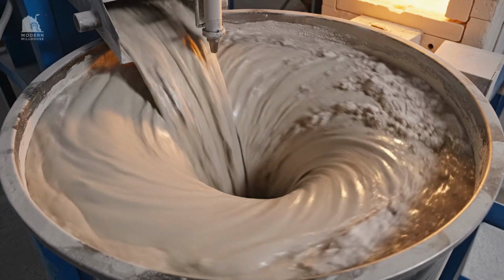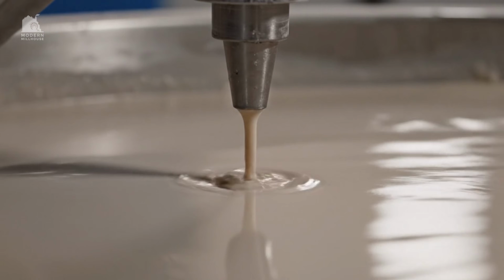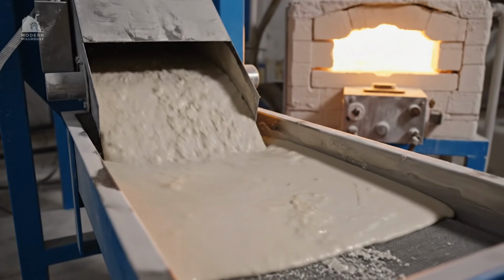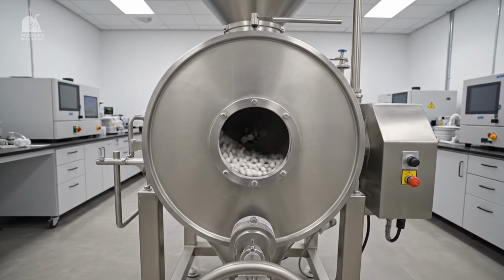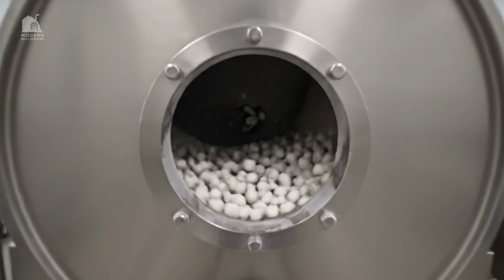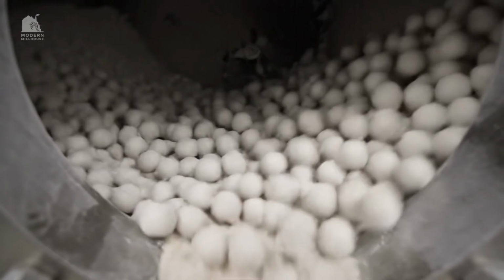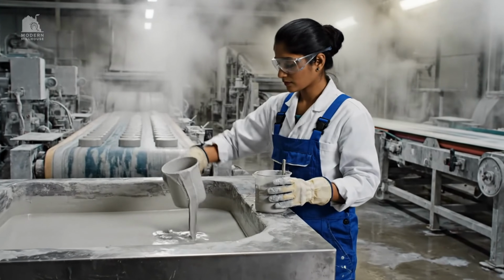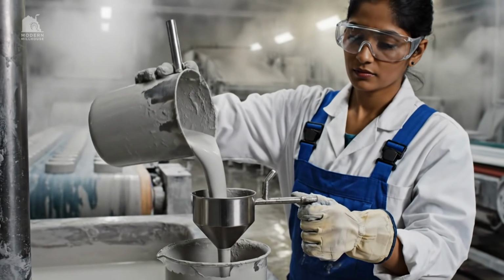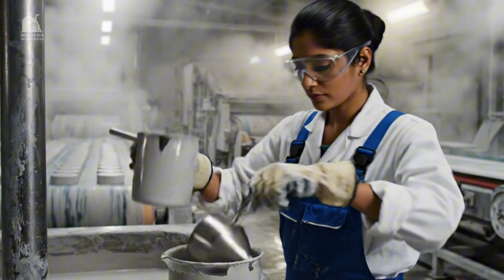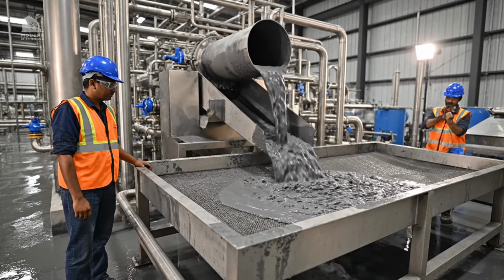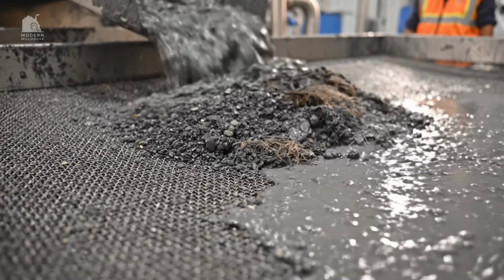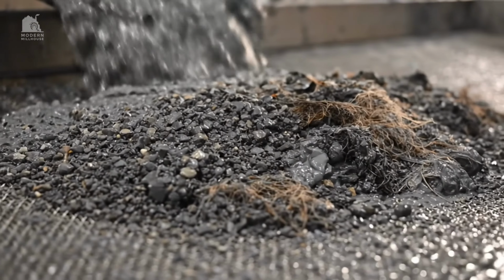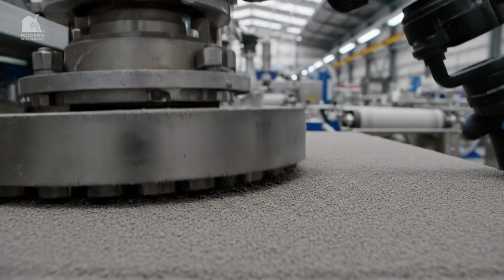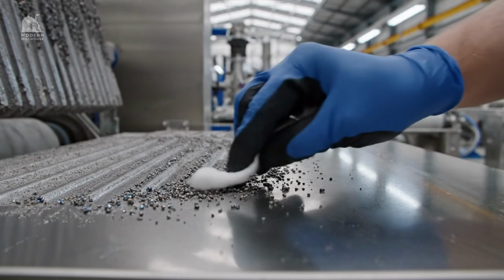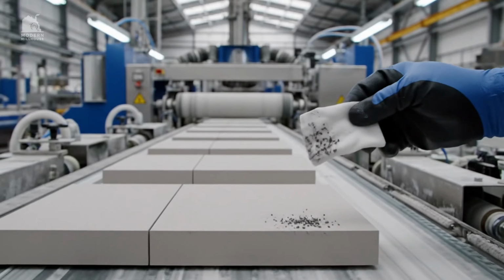After milling, the slurry is screened, then sent through magnetic traps to remove iron particles from equipment wear. Even tiny metal specks can show up as dark freckles after firing, especially under light glazes. Technicians watch pH and temperature because both affect stability and flow. Water systems are often closed-loop, filtering and recycling process water to reduce waste and keep chemistry consistent. A stable slurry produces stable granules, and stable granules produce stable pressed tiles.